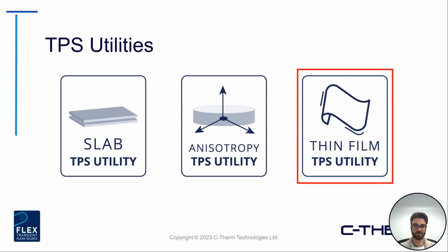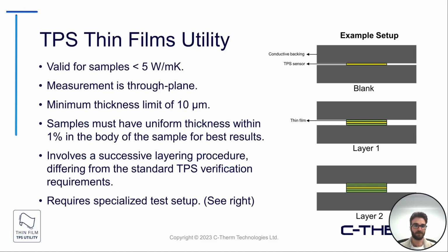And then lastly, thin films. So the thin films utility is probably one of the more popular options when it comes to the TPS. It really allows you to test really, really thin samples down as low as about 10 microns, and these being polymeric freestanding style films. So again, this is not one that we'd really recommend for extremely high conductivity materials. But if you do have thin films, whether they're for electronics, packaging, or different types of applications of that nature, this is a great option to understand the thermal performance, because at 10 microns or even 50, 100 microns, testing options for that size sample can be quite limiting. Or there are things that you need to do to the sample, maybe producing a larger form factor to get a valid measurement. So with the TPS, it gives you a way of directly assessing that type of material.